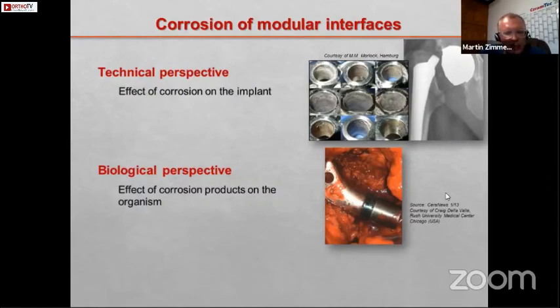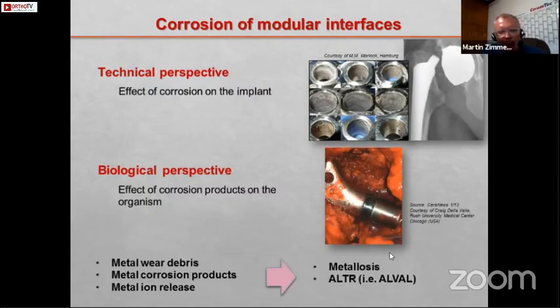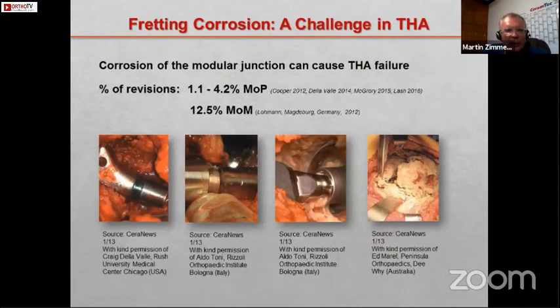More critical is what we call the biological perspective, with all the effects associated with the corrosion products in the organism. As also mentioned before by Dr. Narinder, we have metallic wear debris produced, corrosion products, ions, and all this causes the problematic of metallosis and ALTR. So that's a serious issue that we try to avoid. If you look in the recent literature about the occurrence of fretting corrosion in vivo, you see that following the different publications, we can have up to 4.2% of revision with metal and polyethylene articulation, specifically due to fretting and corrosion. It was a much higher rate with metal on metal, due also to the fact that the metal on metal creates all these ion aspects, coming from the interaction between the head, the femoral ball head, and the taper of the stem.